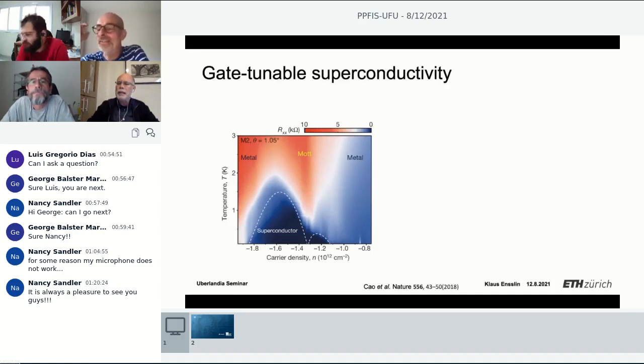Well, thanks, Carlos, for this question. In gallium arsenide, you can change the electronic G factor, the spin G factor, by 10% on a good day. You cannot change it by a factor of 2 by shifting wave functions. The G factor I was talking about here is the valley G factor. I should emphasize that. It's not a spin G factor. The spin G factor, within the accuracy that we can measure, doesn't change.